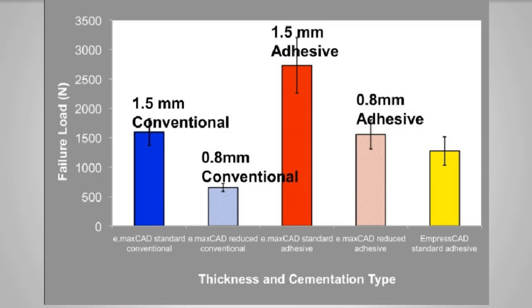If we look at the conventional versus the adhesive cementation, obviously the reason that we recommend adhesive cementation with lithium disilicate as the go-to way to cement it in whenever you can, you get more strength. But more important here, look at 1.5 millimeters conventionally cemented compared to the load to failure strength of just 0.8. Dramatic decrease in strength. The same thing applies to the adhesive. Even though we get more strength than any other method here, we notice that we get a real drop-off in the load to failure by reducing that material thickness. So that's an important thing to remember. But we don't need 3 millimeters of material. That's kind of the point I'm making. So we need the right amount.